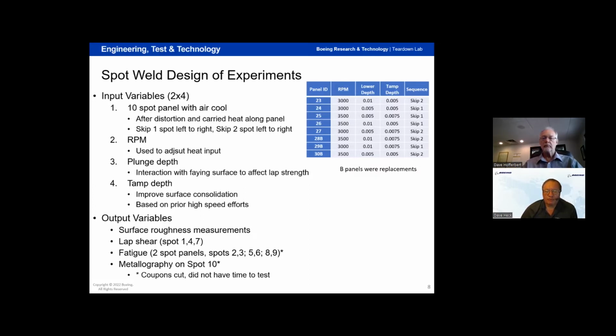So a few more things I want to point out here that were on slides earlier, but didn't make it into this set. With any friction welding process, your primary variables are what your material types are, what the heat treats are, and what the thicknesses are. With each of those changes, you have to come up with a different set of parameters that'll give you the best set of properties, and you have to lock that in. In this case, we were looking at, again, 7075 and 2024, but one was 020 and the other one was 030 inches. That's on the next slide, Dave. See, I'm jumping the gun.